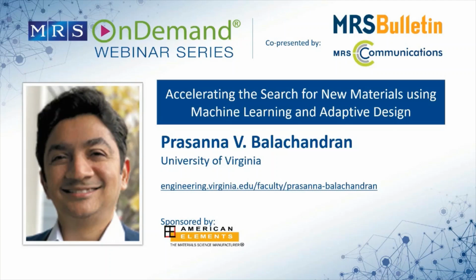Hi, Matt. This is a great question. And I would tend to agree with your assessment and the common opinion that ML, if used by itself, is actually bad for extrapolation. And in fact, there are demonstrated examples that show this behavior, which is the reason why we strongly believe that ML alone can be suboptimal for accelerated materials discovery. On the other hand, if we can augment the ML approach with uncertainty quantification and utility functions, in other words, optimal learning, then there's a potential for us to actually get out of this local minima, where the ML models typically reside, and help us potentially explore the search space, which is where the chance for discovering new materials with properties better than what we already have can potentially happen.